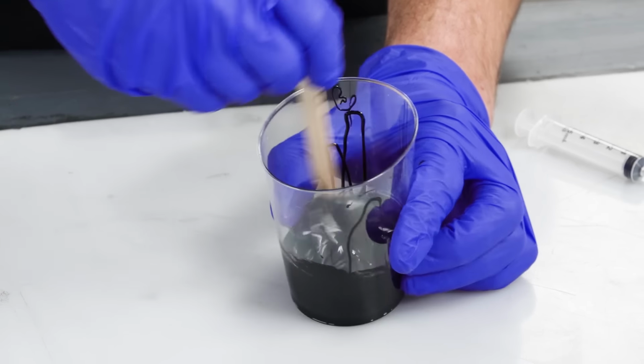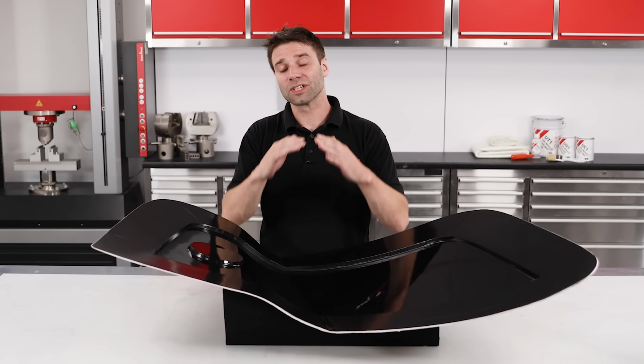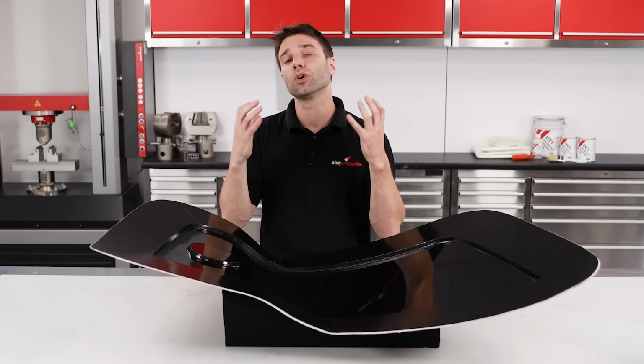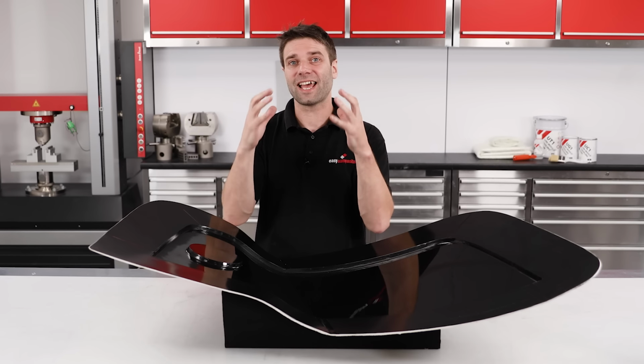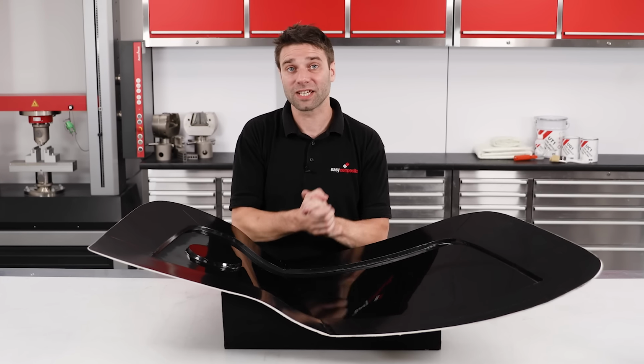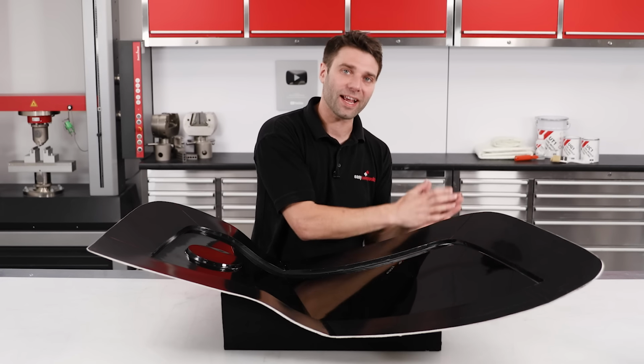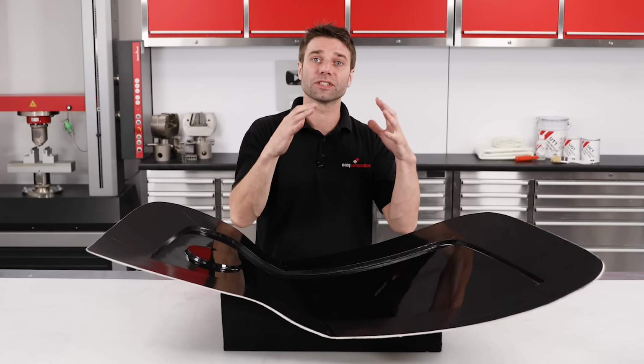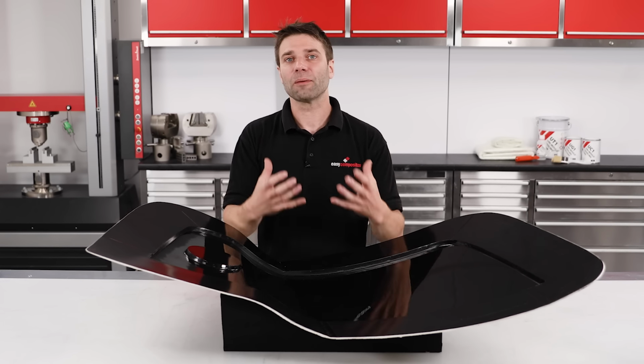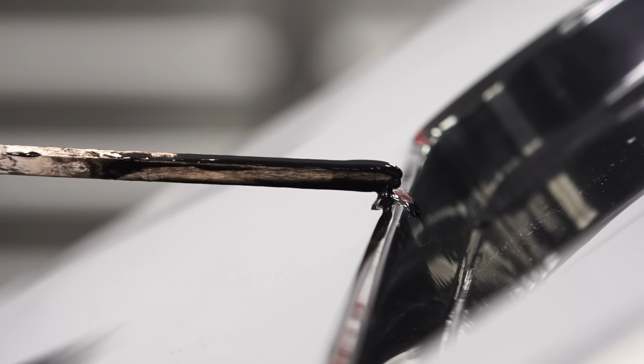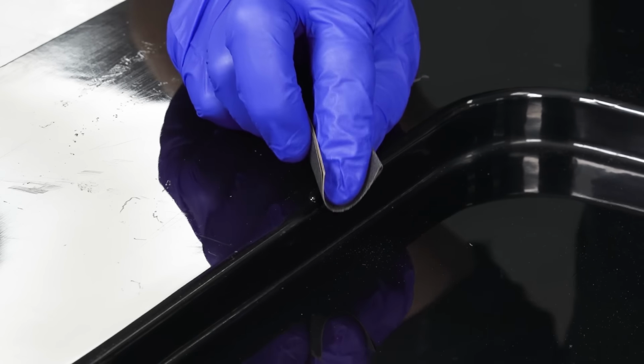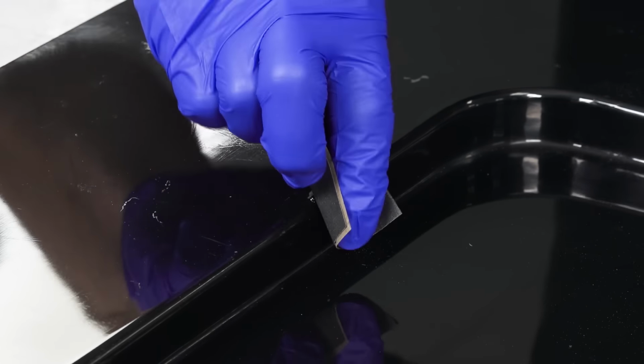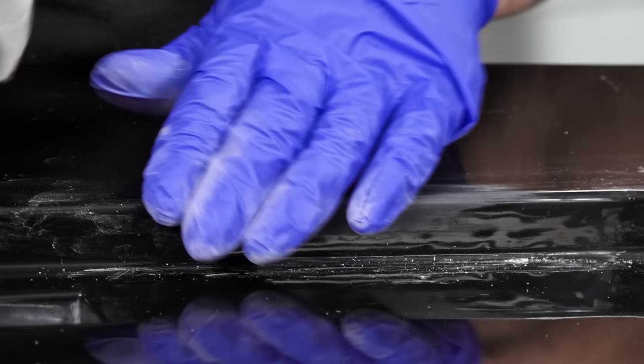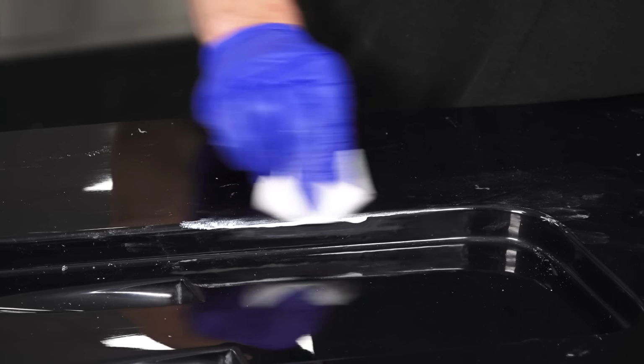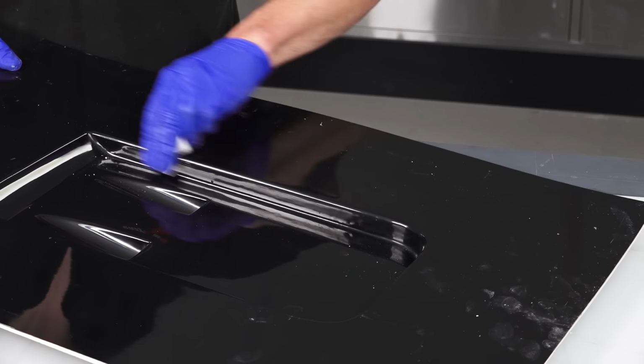The reason for this is, like most polyester and vinylester gel coats, the surface where it's exposed to air won't cure fully, and that can leave a thin, tacky film, which makes sanding and polishing them challenging. But by adding in that wax into the solution, it will create a seal over the surface, meaning that it can cure fully, allowing for easy finishing in the end. This gel coat is applied so that it sits just proud of the surface of the surrounding material. Once the gel coat repair has fully cured, it should be sanded in flush, working through the grades to 1200 grit or maybe higher, before polishing again with NW1 compound to leave a seamless repair.